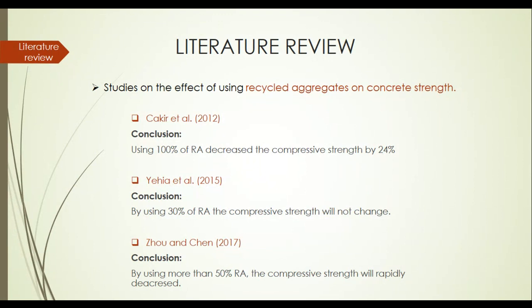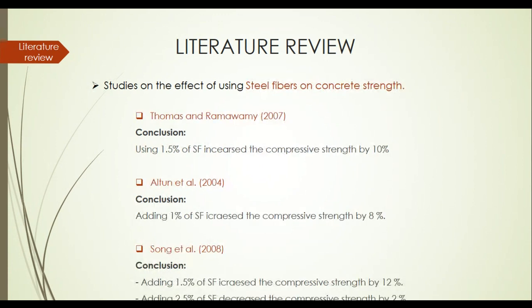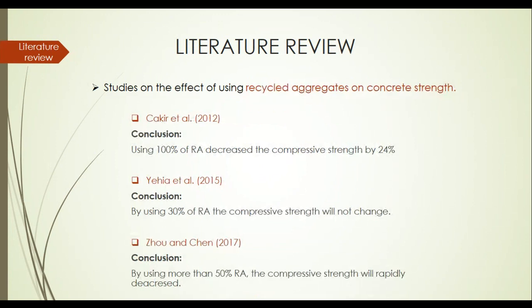Yehia et al. 2015 also ended up with a conclusion saying that 30% of the recycled aggregate will not do much change on the compressive strength. Actually, Zhou and Chen, 2017, said any percentage more than 50% will start to dramatically affect the strength of the concrete. So in general here, we can conclude that the addition of recycled aggregate has a bad impact on the strength of the concrete.